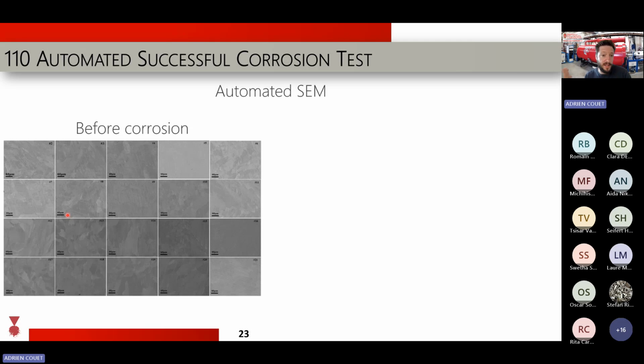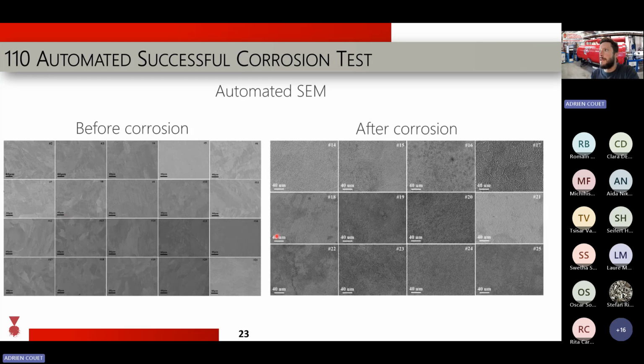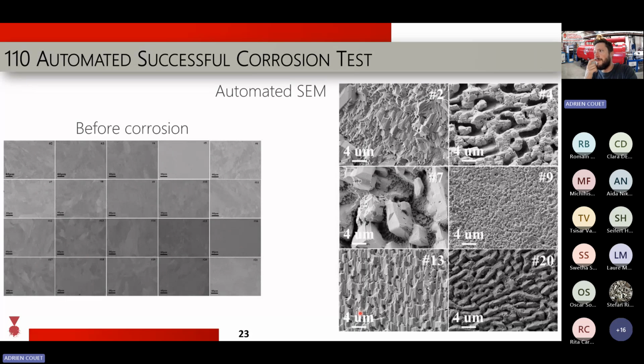You have to decide if you want to go quick and it's not going to be as nice, or very precise, high fidelity, but it's going to take a while. And I guess we should do both, right? It's important to do both. But then after corrosion, you see this kind of feature that appears at the surface of the alloy. And if you look closely, you see very interesting patterns, right? You have various patterns that are, of course, related to crystallography, but not only. The scale of this is way smaller than the grain size. So we are wondering what is actually leading to those interesting features that you observe, faceted versus maybe more ligament type of morphology.